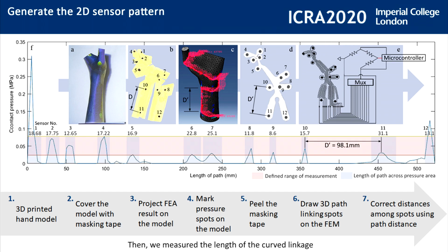Then we measured the length of the curved linkage which fits to the surface of the hand between any two pressure spots in the FEA software. The length was used to adjust the rough 2D pattern. Thus, a relatively more accurate 2D sensor pattern can be achieved.